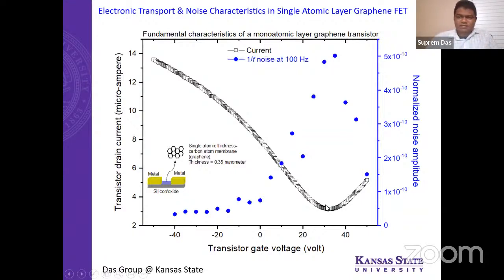And that's because, as we are explaining at the Dirac point, you can have such control of the number of carriers that the mechanism of noise is completely different. Now you can see there is an offset voltage from 0 to 30 volts. That's primarily because graphene is sensitive. If it's not clean enough, it is very hard to get the Dirac point at 0. Of course, these are our initial results, but we now have very good control so that we can bring it to 0 at the Dirac point, so that we can ensure that it's not completely p-type or n-type doped. Now this is bad, but it can also be good. If you know how to manipulate it, you can dope it either p-type or n-type. So again, it depends on what angle you are looking at, but if you can control it, you have the ability to change the charge carriers in the graphene channel.